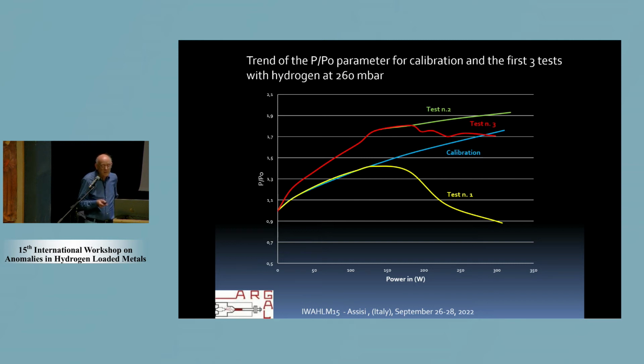It means that hydrogen was absorbed by the material in a quite strong way, because when we stopped the experiments and returned to ambient temperature, the pressure decreased from 260 millibar to 60 millibar. Being the volume about 3 liters, the amount of hydrogen absorbed was quite high, considering that the weight of the powder was 7 grams.